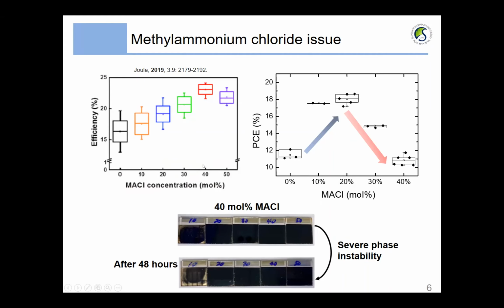They were able to achieve the highest efficiency with the use of 40% MACl. However, our results came out different: our optimum MACl amount is somewhere around 20% MACl, and the efficiency sharply decreases when the MACl content is increased. We also found that with 40%, the stability becomes very unstable and the phase instability becomes severe, so that the alpha phase readily converts back to the delta phase within a day.